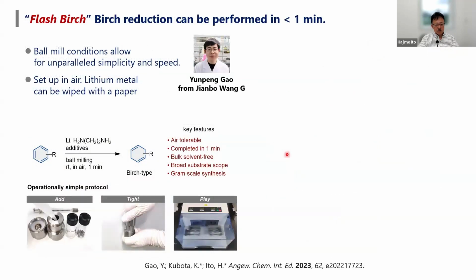But we tried using ball milling reaction conditions for Birch reductions, and we found that the reduction can be conducted very easily just by putting lithium metal inside the jar with substrates and shaking the jar.